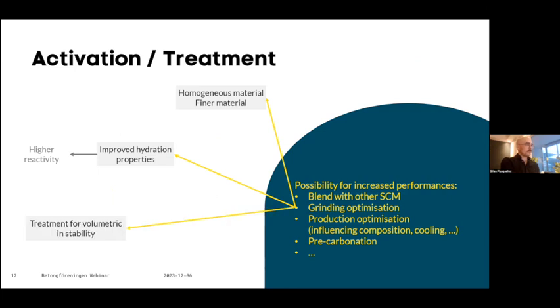It can also solve the expansion problem, especially in the case of wet grinding, by getting rid of the free calcium oxide. You can change the actual way the slag is produced. By direct collaboration with the producer, it's possible to influence the chemical composition and therefore again improve the hydration properties. If you speed up the cooling, you have a more amorphous content,